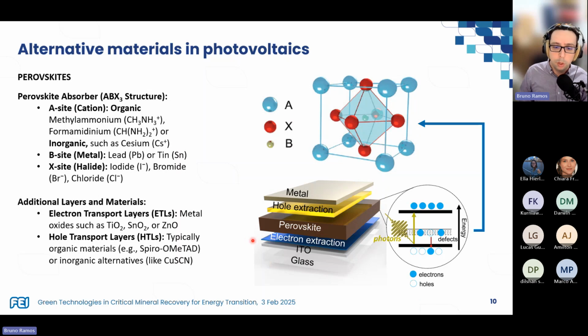So in this picture at the bottom, we show the typical structure of a photovoltaic cell. The perovskite, which is responsible for absorbing light and promoting the photoelectric effect, is the absorber, but we also need a hole extraction layer, an electron extraction layer, and a transparent layer, which is often made of glass and ITO. ITO is an indium tin oxide layer, a sort of transparent semiconductor, which we can use to make the electric contacts. For the hole extraction layer, we typically use organic materials, but we can also use some inorganic materials like copper thiocyanate. And for the electron extraction, we normally use metal oxides like titanium dioxide, tin dioxide, or zinc oxide, which are also very good semiconductors and very well established with a good supply chain.